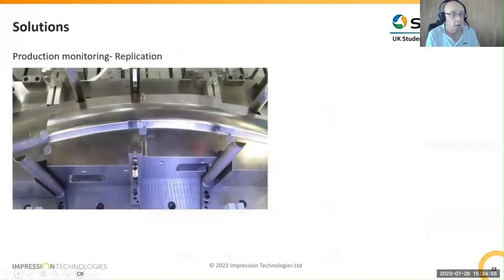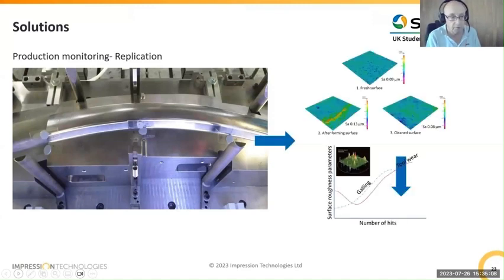Next, to monitor, another thing that we do with the dies is we monitor the surface over a period of time, and we do this by using 3D profilometry. Now, it's not the easiest thing in the world to take a die which is maybe 2 meters long and 1.5 meters wide and drop it onto the bed of a 3D profilometer. So we have to do that by taking replicas at various points during the process.